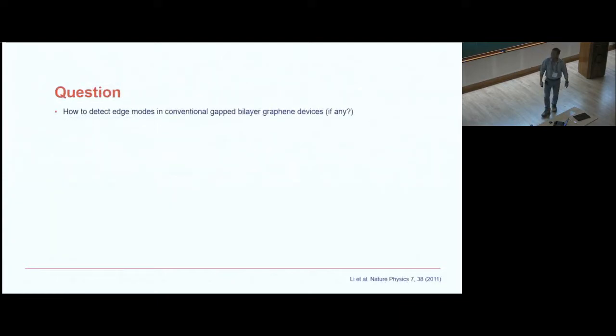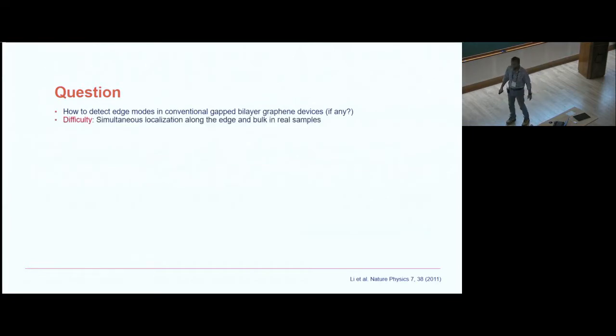So the question that came up, and we started looking at, is how to detect the edge modes in conventional bilayer graphene devices. Gap it and then see if there are edge modes. The difficulty is that the gap and the edge both localize simultaneously. Because when I apply an electric field, I'm gapping out the bulk, whereas the edges are being localized by the disorder at the edges. Okay?